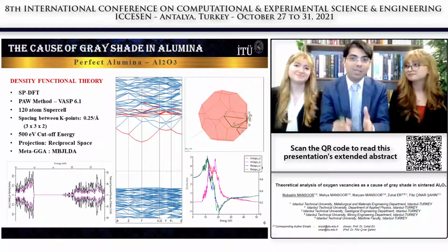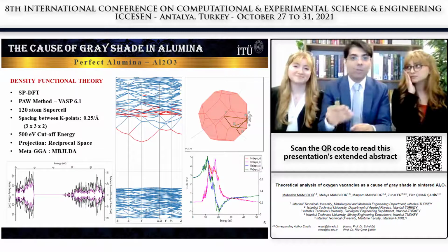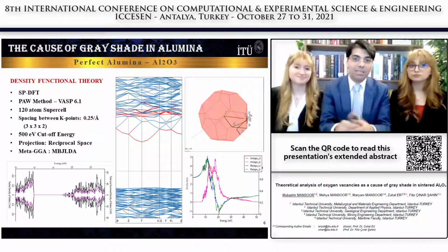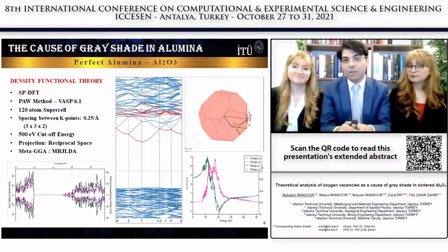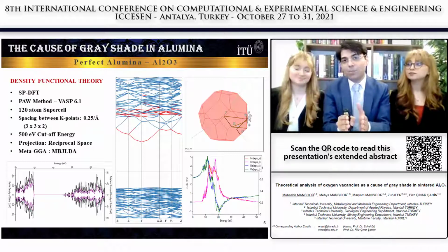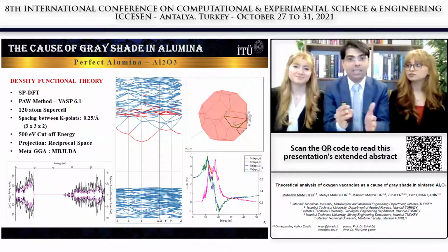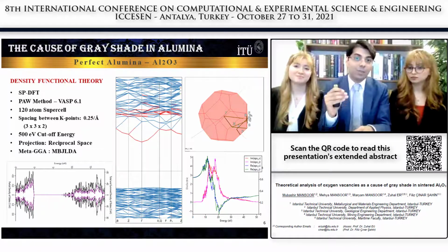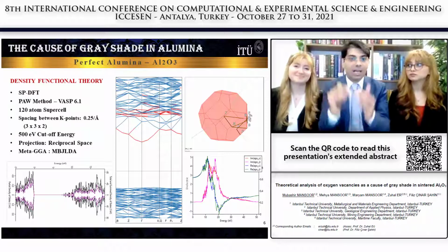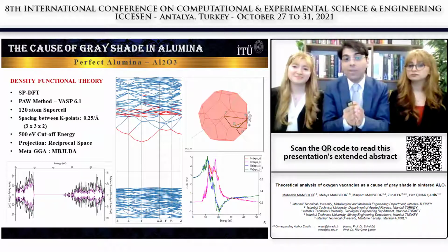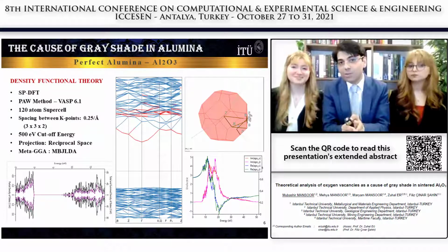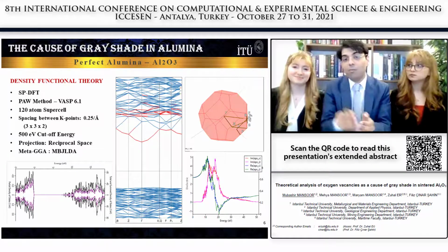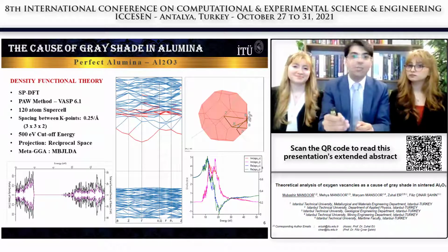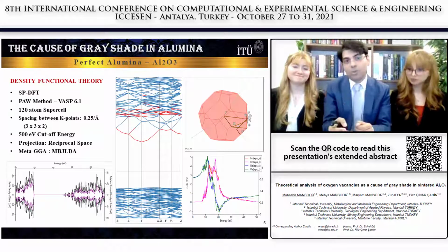So we applied spin-polarized density functional theory with the projector augmented wave method as implemented in VASP. And we have calculated the dielectric function by using the modified Becke-Johnson local density approximation as our meta-GGA exchange functional. Here's a band structure of the pure and perfect alumina cell without any defects, with the valence band of the p orbitals and a conduction band minimum at the gamma point made of the s orbitals. The idea is to see what are the defect levels induced by oxygen vacancy. Once we know the dielectric function, then we can use the complex part to calculate the absorption spectrum.